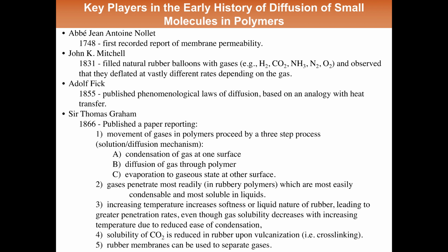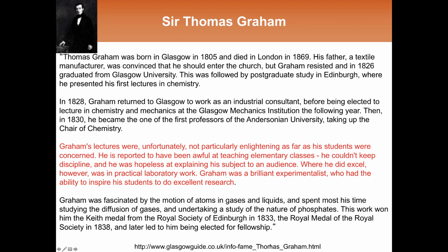And this is today known as the solution diffusion mechanism, and now well over a century and a half later, this mechanism is the fundamental backbone behind which we understand the transport of small molecules through all types of non-porous polymer and polymer composite materials. He also made a number of other very important observations that turn out to be absolutely correct, including that these natural rubber membranes can be used to separate gases.